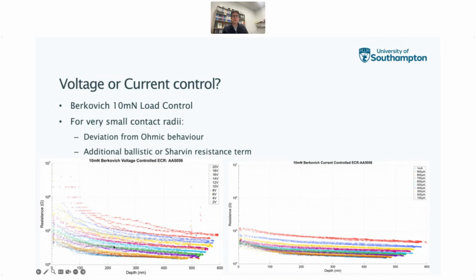But you notice as the tip radius gets smaller and the depth gets shallower, we start to deviate from that linear behavior, because we're departing from the ohmic behavior and getting an additional resistance, known as the ballistic resistance or the Sharvin resistance. This is where the mean free path of the electrons as they move across the contact is of the order of magnitude of the diameter of the contact itself. And so that's something that we need to avoid.